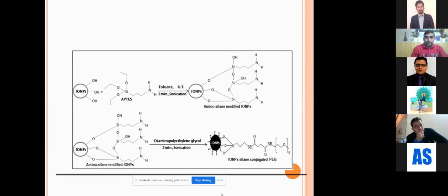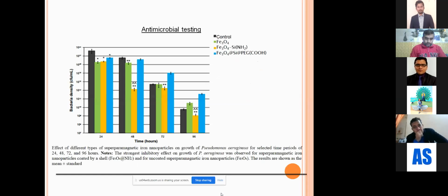Anybody can synthesize iron oxide nanoparticles and can optimize or functionalize these iron oxide nanoparticles with aminopropyltriethoxysilane or with carboxysilane. That is the advantage, and we have done this comparative analysis by conducting the experiment I told you about on Pseudomonas aeruginosa, and we have seen the range of the growth kinetics with the time it has passed through.